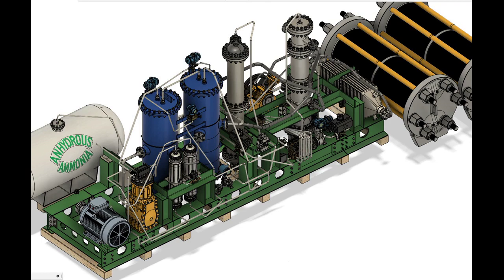Promoters can be classified into two categories: structural promoters and electron donors. In the case of ammonia synthesis, potassium performs the function of an electron donor, donating electrons to the iron, facilitating the breakage of the diatomic nitrogen bond. Calcium serves as a structural promoter, blocking certain catalyst sites and exposing more active sites, what is termed 110, 111, referring to the morphology of the crystal structure and its number of faces.